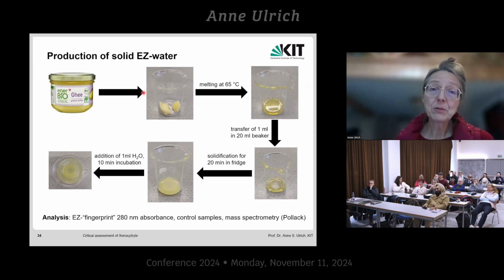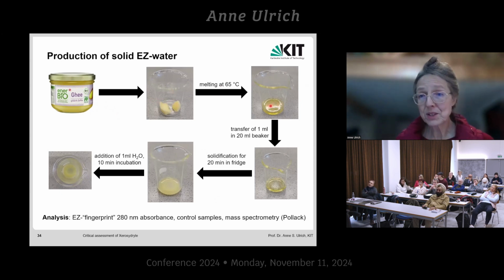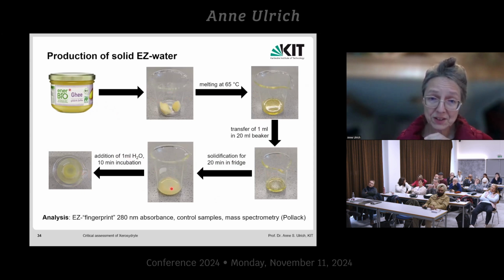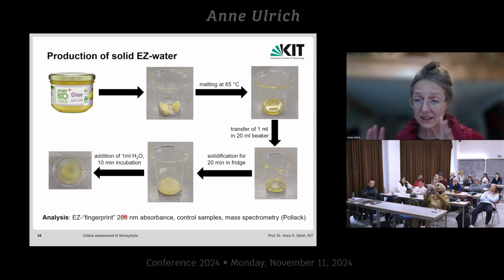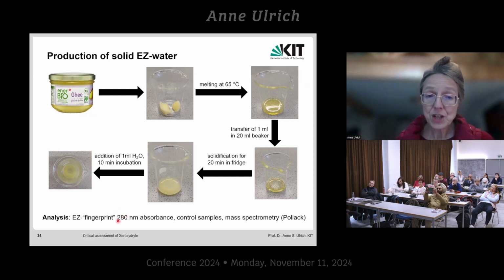From the ghee, you first take a spoonful into a glass container and melt it. Now, from the molten solution, you transfer 1 milliliter into a new, fresh, clean glass container and let it solidify 20 minutes in the fridge. And then you add 1 milliliter of water, let it incubate for 10 minutes so that just the surface touches the water. You siphon off the water and do the analysis. So this is very clearly explained.